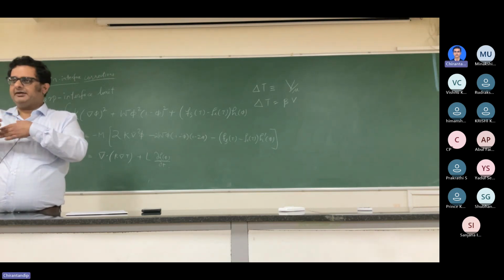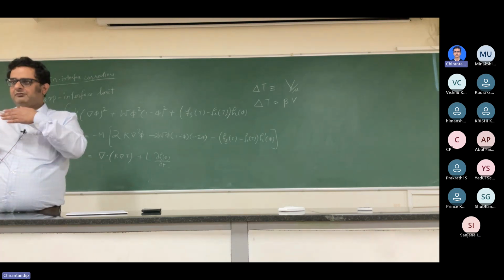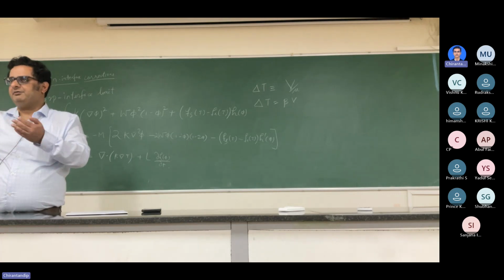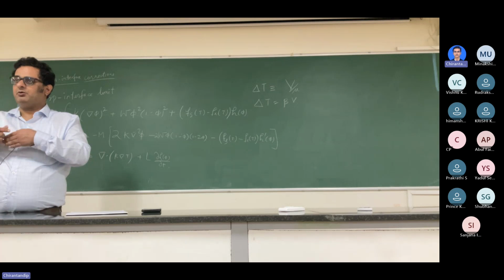If it's atomistically rough, typically they have enough sites to go into the interface. And if that is the situation, then the undercooling for that activity is really very small, right? So the two situations are, if you have a smooth interface, that's typically when you have an anisotropic faceted interface, you typically have a situation that your interface being smooth, you have some interface kinetics in the problem.